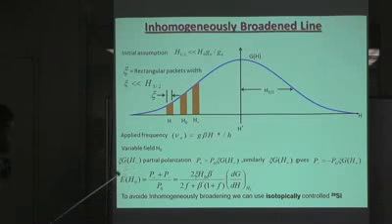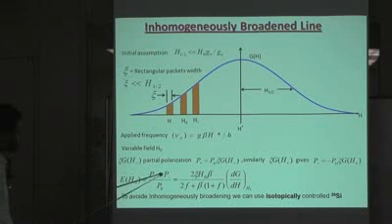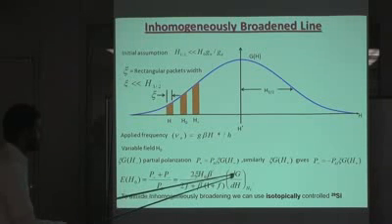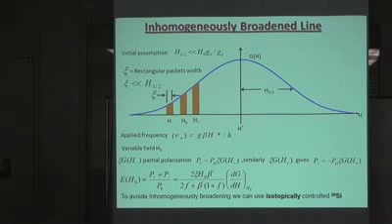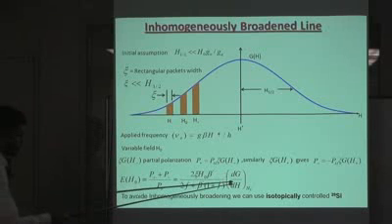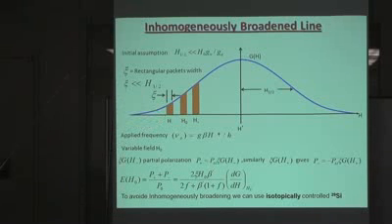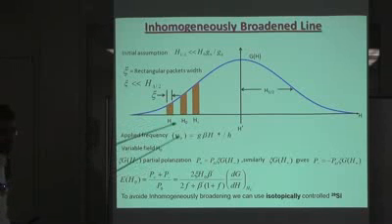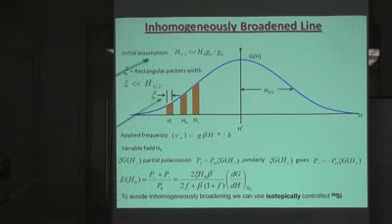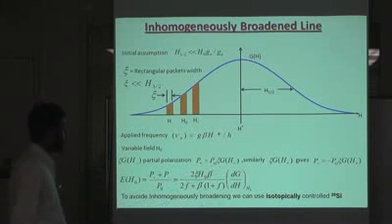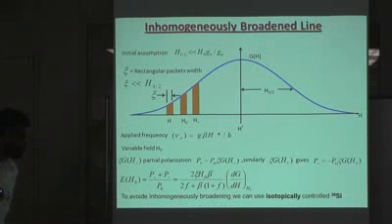So there is a reduced enhancement, which is defined by P plus plus P minus divided by P naught, and which is proportional to dG by dH, meaning the first derivative of the EPR line, which I showed in the previous case: in my field dependence we have the first derivative of the polarization value. So to avoid an inhomogeneously broadened line, we can use isotopically controlled silicon.